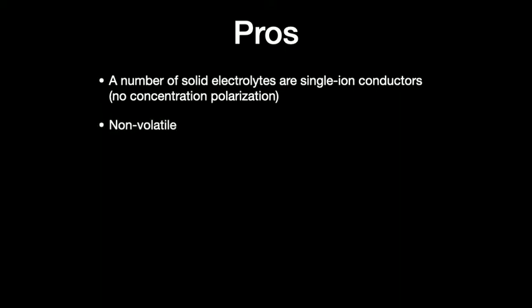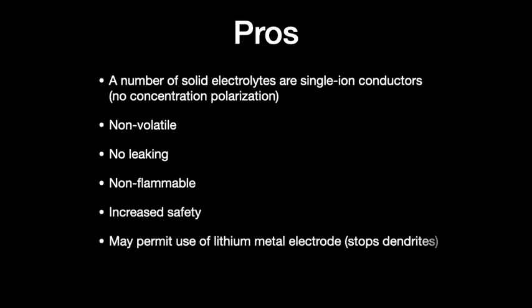Solid electrolytes are non-volatile, no leaking, typically non-flammable. This should lead to increased safety and may permit the use of lithium metal without the formation of dendrites. If it's the appropriate solid electrolyte, it should stop dendrites. So that means it's possible to build a fully solid state battery, but with some of these caveats.